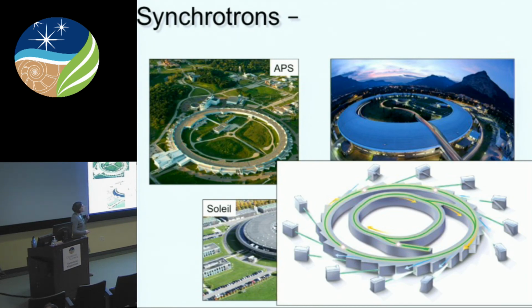So there's a cathode that's heated to very high temperatures, generating electrons. You use a linear accelerator to get those into what's known as a booster ring. Here, the electrons are accelerated to like 99.999% of the speed of light. After they reach that speed, they're injected into the storage ring, where there are some more nines after it to the speed of light. And when a charged particle is accelerated radially, you get electromagnetic radiation, or X-rays. Tangentially off of the storage ring, we have beam lines which basically just siphon off this electromagnetic radiation. It's very high energy X-rays, so we can see through things like aluminum or other metals that we use to contain our samples at high pressures.